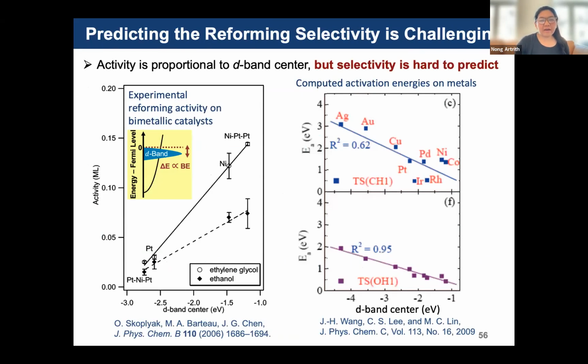But as already known in the community, predicting the activity is well established by looking at d-band centers. As you can see here on the left-hand side, we have the d-band centers and the activities, and then we can identify what could be a good catalyst, because a low activation energy means a good catalyst. There are also many different types of reactions already. But predicting the selectivity is really hard, because you have to know all of the reaction paths. So this is a problem in the community.